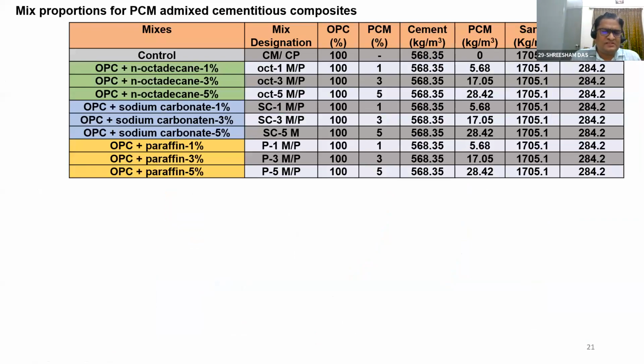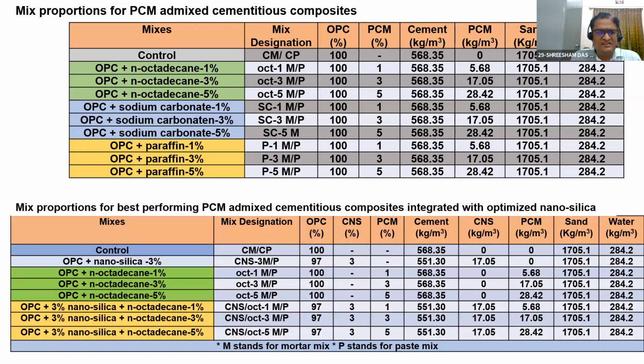So these are the mix proportions: control, then OPC plus n-octadecane 1%, 3%, 5%, sodium carbonate 1%, 3%, 5%, then OPC plus paraffin 1%, 3%, 5%. So we tried different proportions, and similarly the next stage, OPC plus nanosilica 3%, then OPC plus n-octadecane 1%.